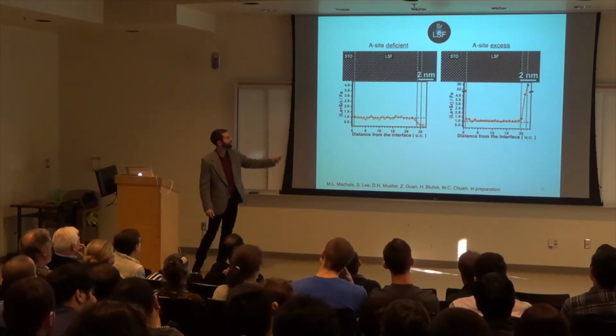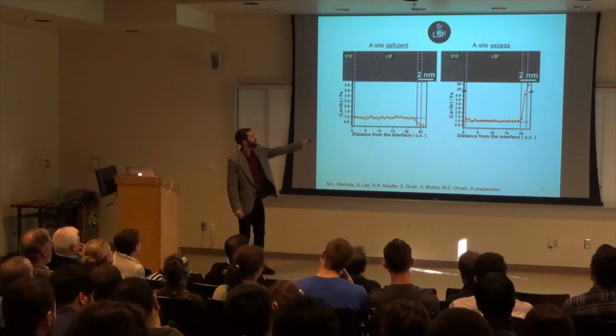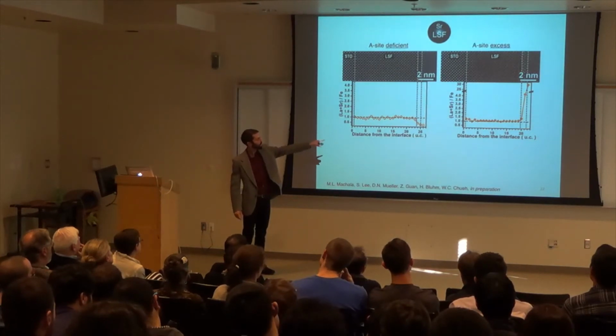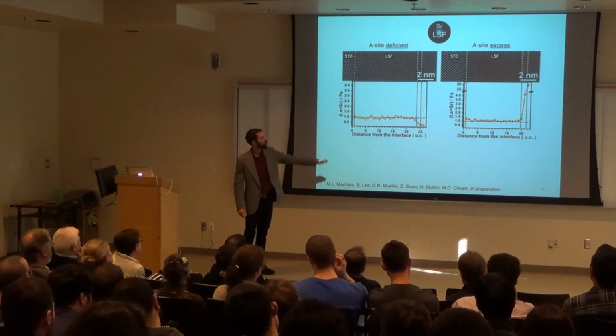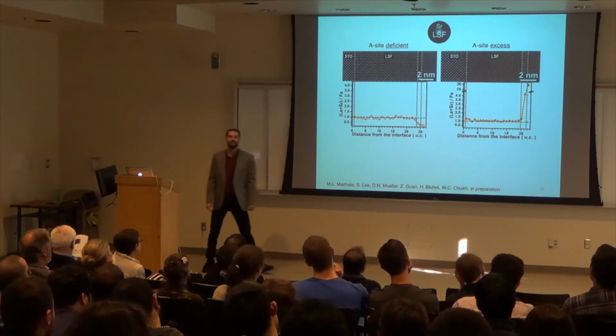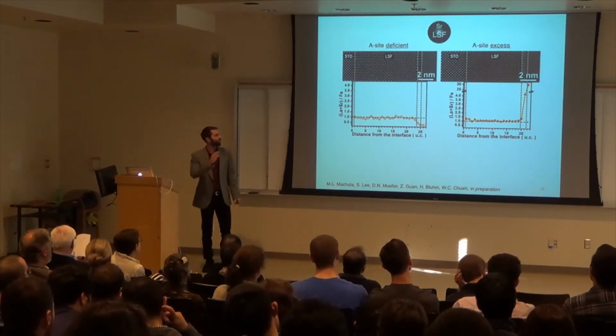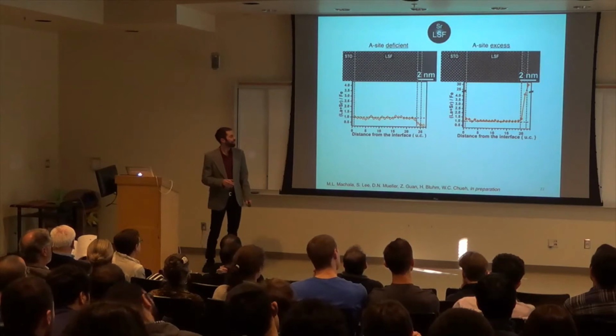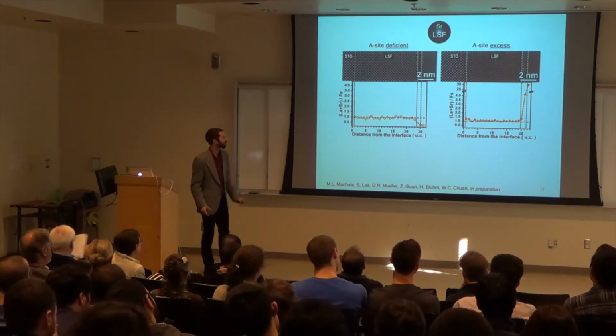When we compare this, the A to B site ratio, to that of the other sample, we see that it's relatively uniform in the bulk. But then it jumps up at the termination layer, which is very, very different. So that is A site terminated.